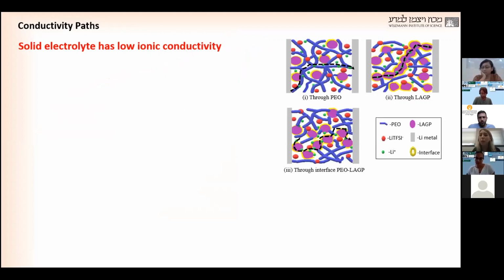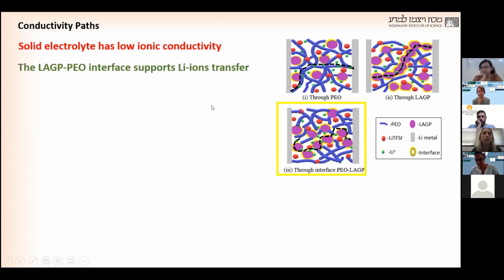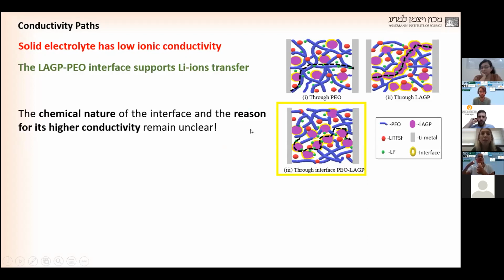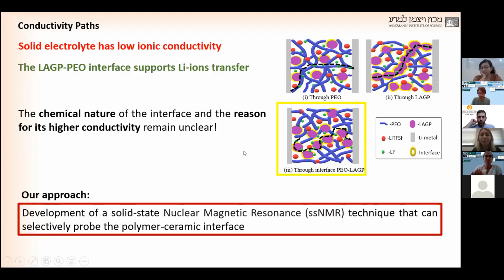According to the literature, there are three options for the path of lithium ions inside the composite. The first is through the polymer chains. The second is through the ceramics. And the third is through the interface between the polymer and the ceramics. It was found that the interface is the best path for lithium-ion conductivity. So it's important to understand this interface, but the chemical nature and the reason for this higher conductivity remain unclear. So our approach is the development of a solid-state nuclear magnetic resonance (NMR) technique that can selectively probe this interface.